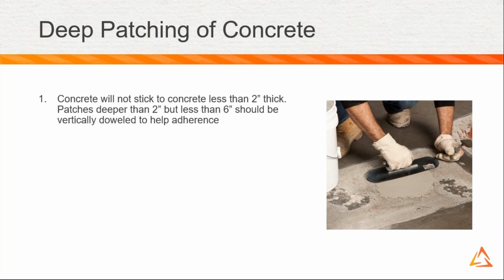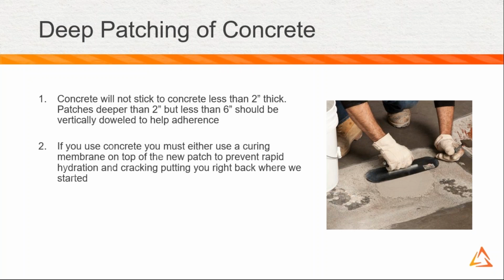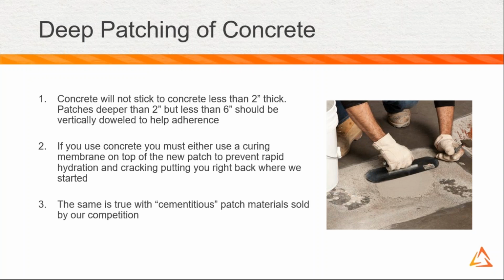Concrete will not stick to itself less than 2 inches thick. Patches deeper than 2 inches thick, if you're going to pour concrete on top of it, have to be doweled, vertically doweled, so that it will stick to itself. Concrete just does not like itself. If you use concrete, you must use either a curing membrane on top of the new patch to prevent rapid hydration and cracking, and that puts you right back where we started in this presentation.